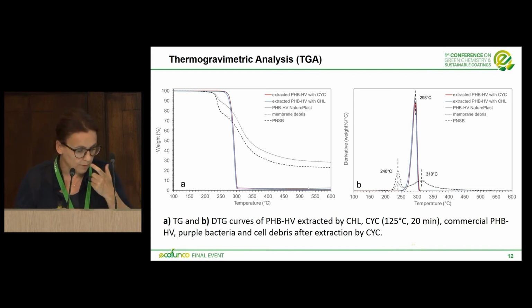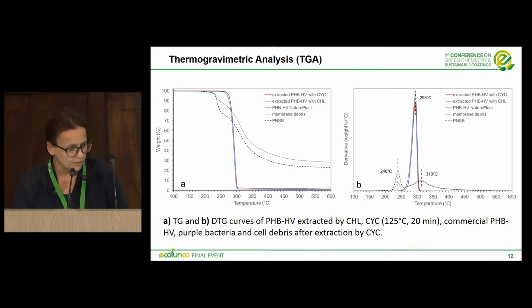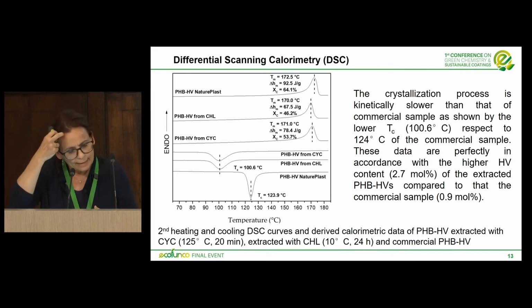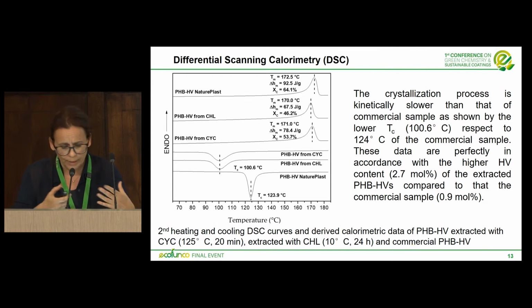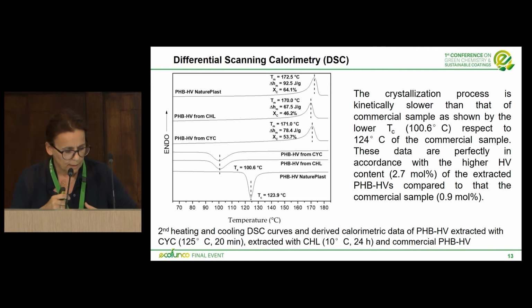In this slide you can see the TG thermogravimetric analysis curves of the starting bacteria, of the membrane debris, and, of course, of the extracted PHB-HV using cyclohexanone and chloroform. And you can see the perfect overlapping between the TG curves of the PHB-HV extracted with cyclohexanone and the commercial PHB-HV by Naturplast. Consequently, this analysis also confirms the high purity of the PHB-HV extracted by cyclohexanone at a higher temperature. So, again, the DSC curves. Also in this case, you can see similar curves of the PHB-HV extracted by cyclohexanone and chloroform compared to the DSC curves of the PHB by Naturplast.